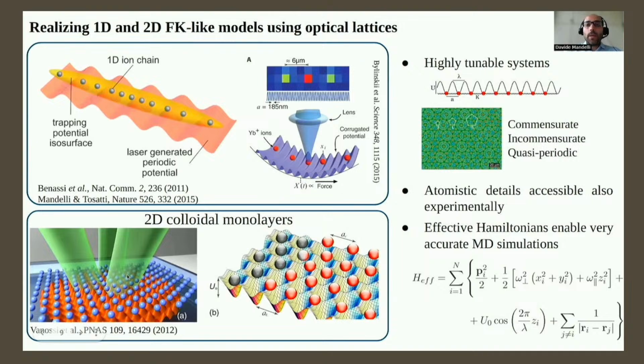Now, there are three main properties that make this system very attractive. The first one is that they are highly tunable, so playing with the intensity of the laser, one can tune the Aubry-like parameters, so the corrugation potential and the periodicity of the optical lattice, and by tuning the confining potential that is needed to keep the charged particles together, one can also tune the lattice spacing of the charged particle crystal and the spring constant. So one can achieve commensurate and incommensurate interfaces, and in the case of 2D colloidal monolayers,